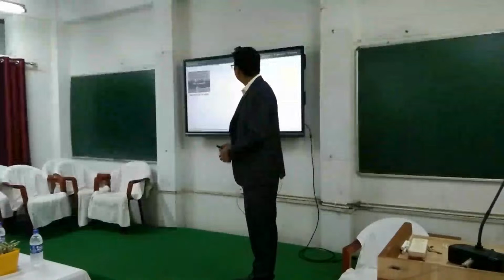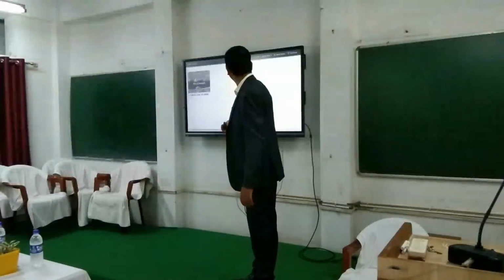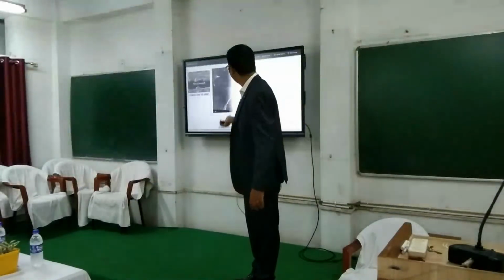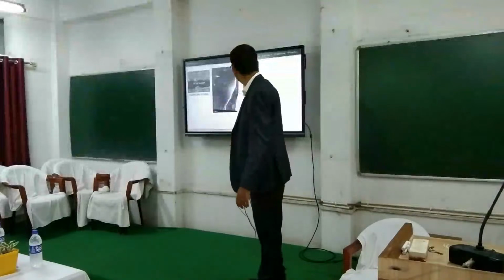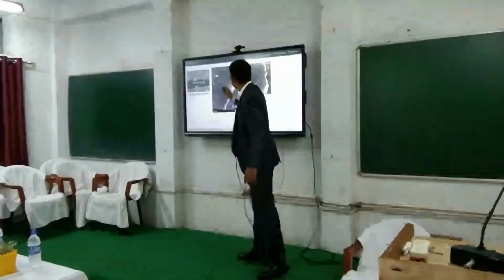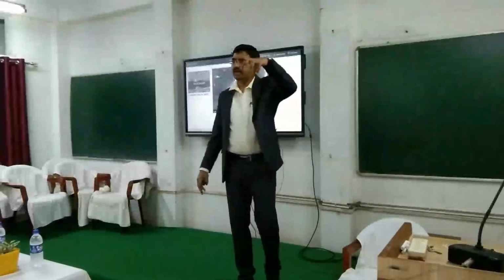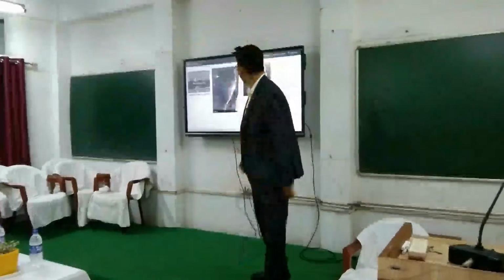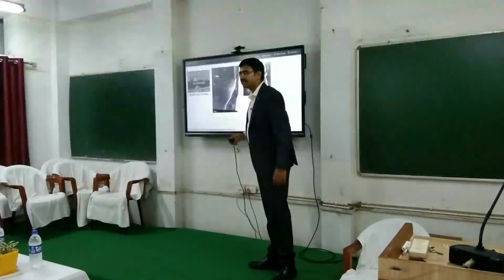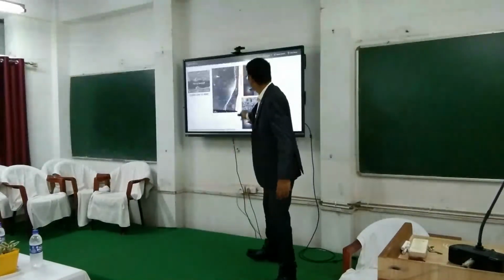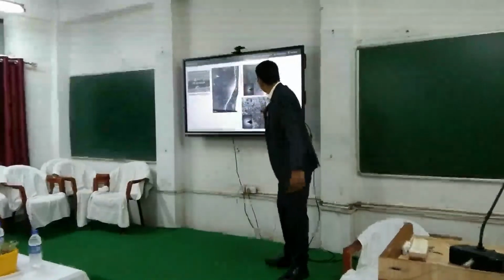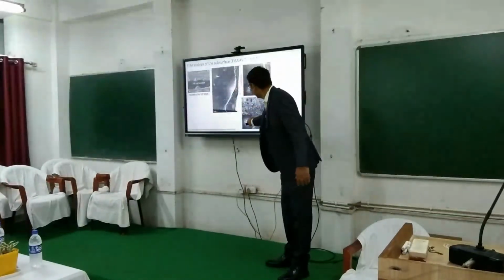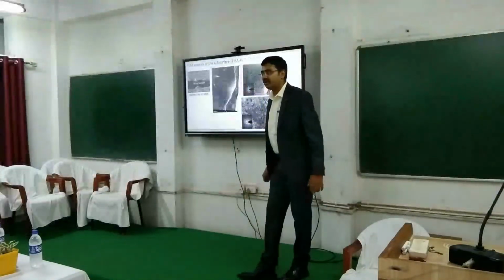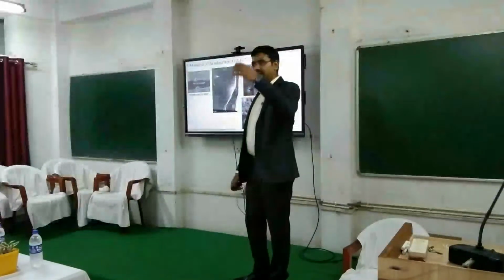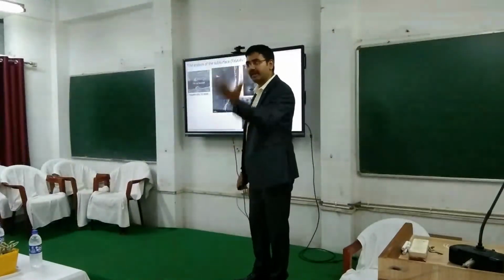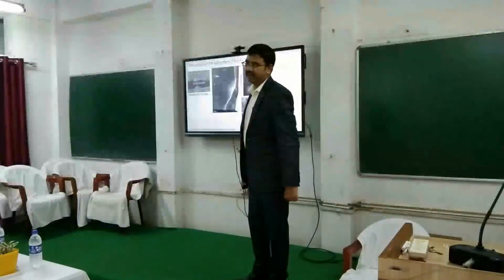Okay. We also did some TEM analysis, and we looked at how the grain structure actually looks. Below the tribolayer, since you have less stress transfer, because the tribolayer has some load bearing capacity, you can see the coarse grain structures. Whereas the region where there is no tribolayer coverage, you see very fine grain structures. This can be seen by the continuous rings of the SAED pattern. So the higher the tribolayer coverage, the better it is in terms of wear and in terms of friction.